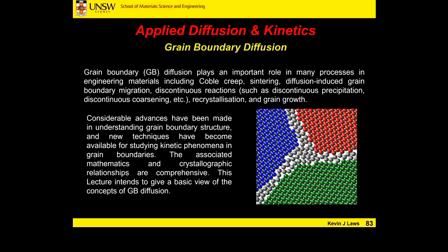of our grain boundaries, as opposed to surrounding crystal structures, in high resolution TEM, and atom probe tomography, where we're pulling the material apart atom by atom, then doing a reconstruction of that. You can actually see where all the atoms are sitting on grain boundaries. You can do concentration profiles within these systems and look at segregation profiles at grain boundaries. Where are things sitting? What is their concentration? And what were the experimental conditions that led to that?